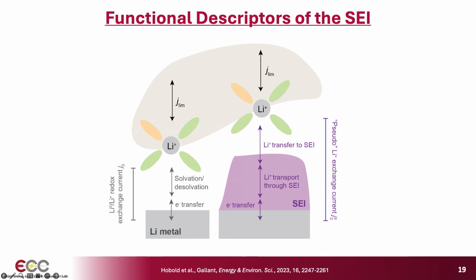We were interested in seeing if we could learn about how the SEI modulates this exchange reaction, because that's fundamentally what it needs to do. It needs to be able to accept a desolvated lithium ion, then the lithium ion has to transport through it, and then you have an electron transfer and a plating reaction underneath it.